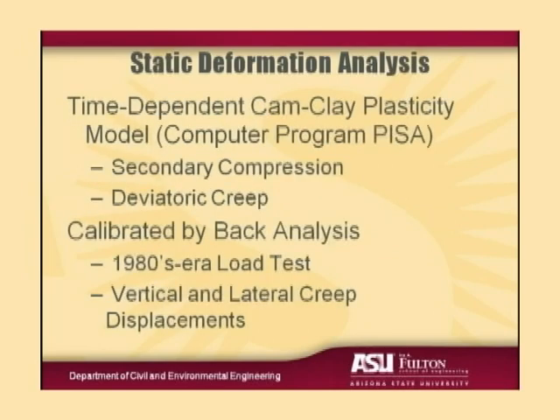For the static analysis, we used a time-dependent Cam Clay plasticity model. We used a computer program called PISA, developed by Professor Morgenstern and his students. Paul Sabatini at Geosyntec was most responsible for this analysis. The program includes secondary compression or volumetric creep and deviatoric creep or drain creep. So we did back analyses of the measured deformations of the landfill, including those inclinometers, to get some best fit properties to plug into this model and then to predict forward for another 30 years.